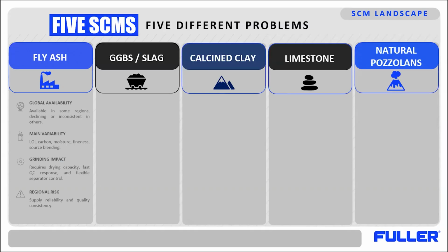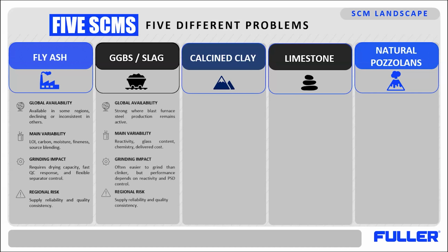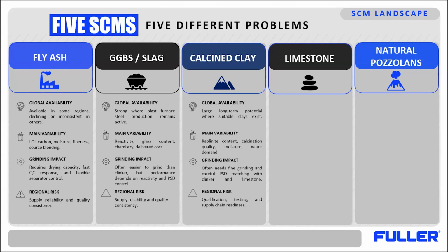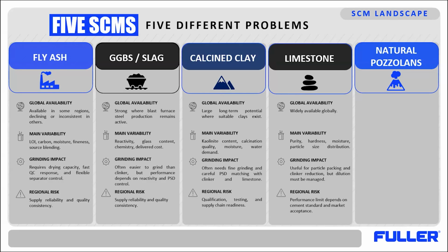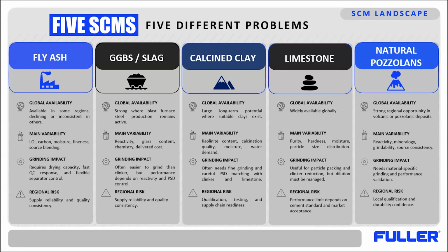For example, fly ash can vary in loss on ignition, carbon content, moisture, fineness, and also source consistency. For slag, performance depends on reactivity, the glass content of the slag, the chemistry, and the supply reliability. Calcined clay has strong potential, but it depends on the kaolinite content, calcination quality, moisture, and water demand. Limestone is widely available, but purity, hardness, moisture, and PSD can strongly affect the final cement performance. Finally, natural pozzolans can be very valuable locally, but they are highly source specific.